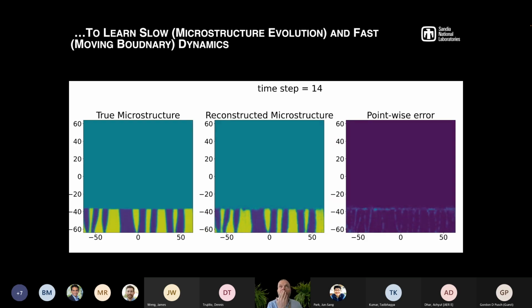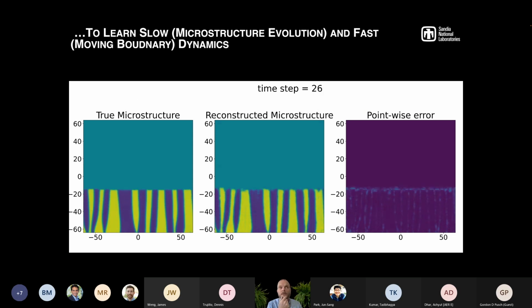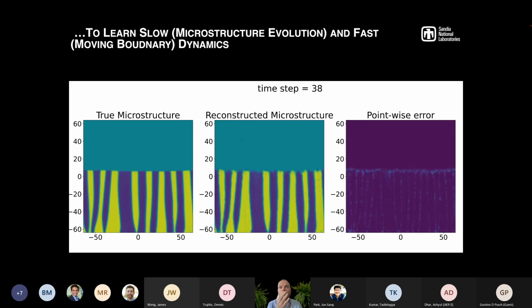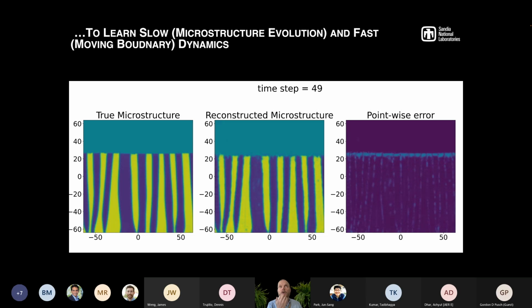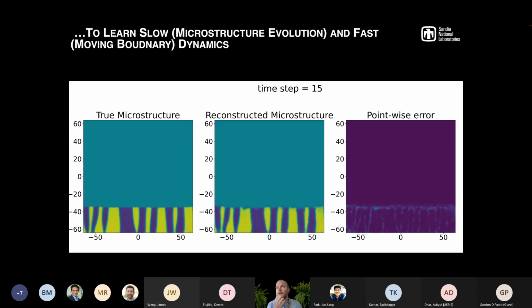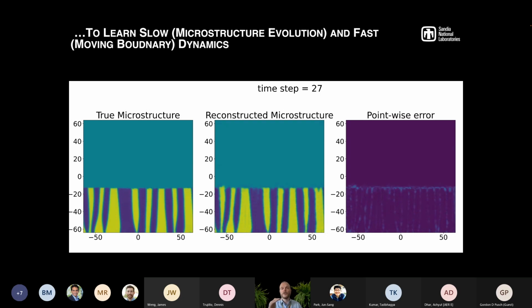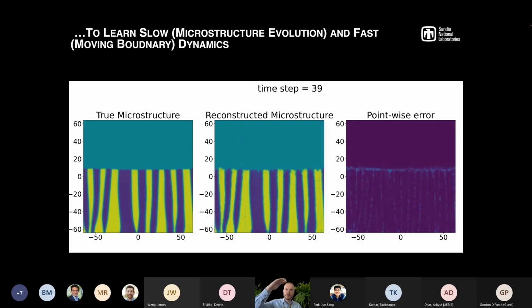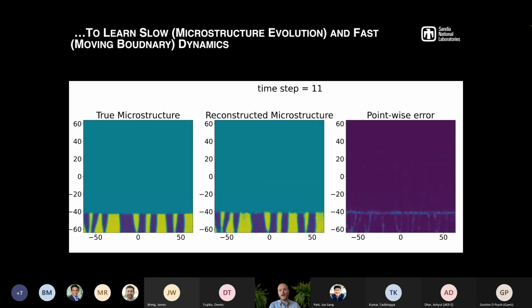And actually what you get is this type of results, where on the left-hand side of your screen, you see the evolution as predicted by the phase field simulation. The middle evolving microstructure is the one predicted by our concurrent strategy. And on the right-hand side is the difference between the two. And so what you see is that not only are we able to accurately capture that moving boundary, so the size of your domain keeps changing as a function of time, but at the same time, we're able to accurately capture the formation of the microstructure, which changes at a much slower time scale.